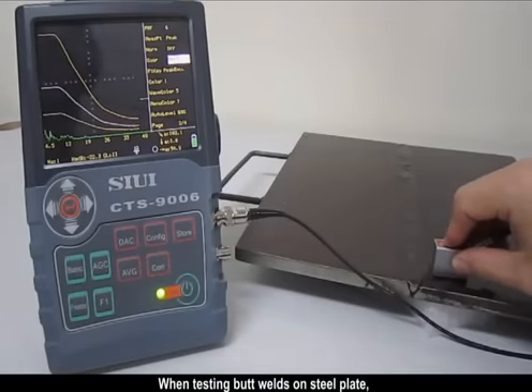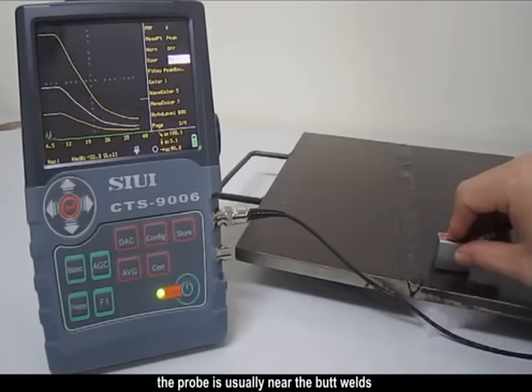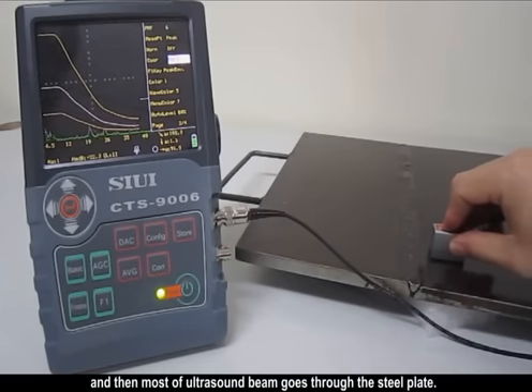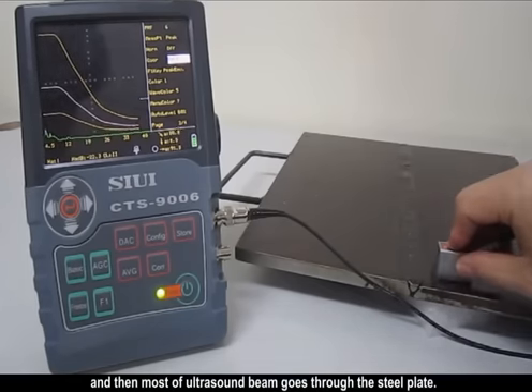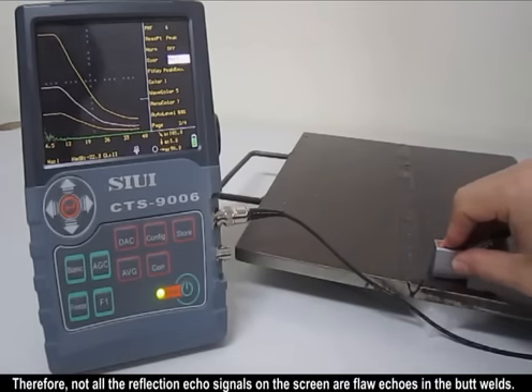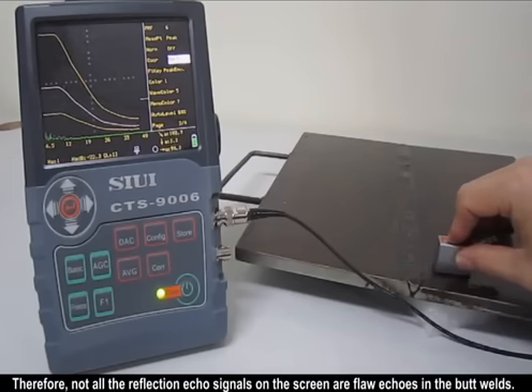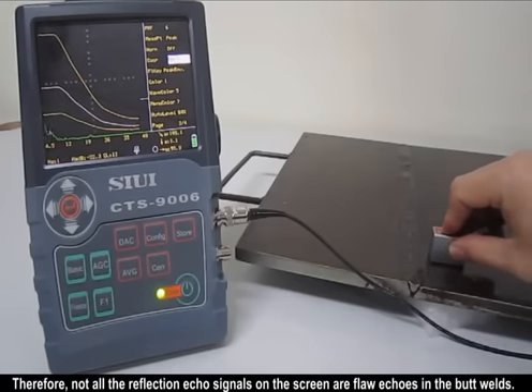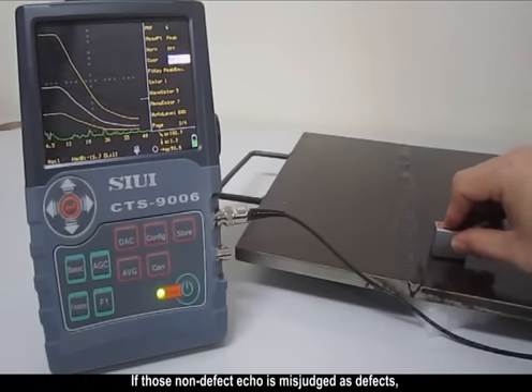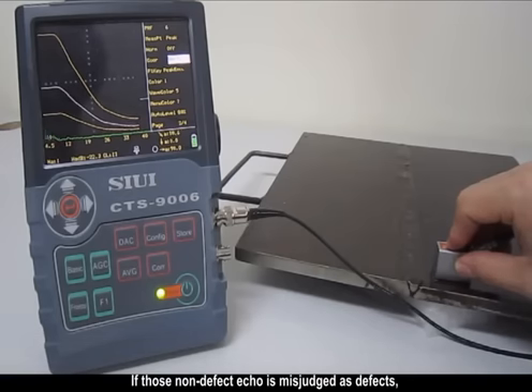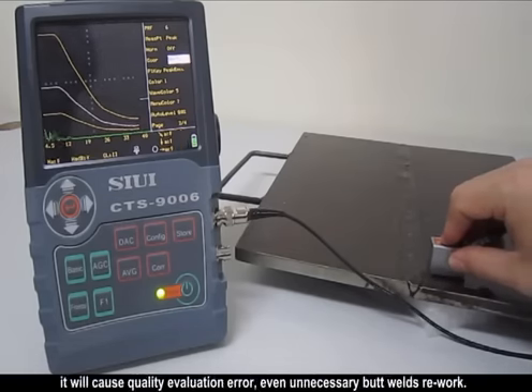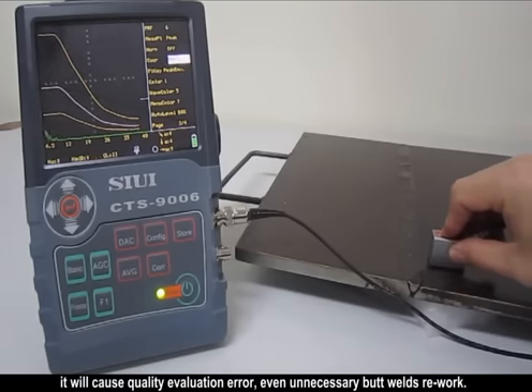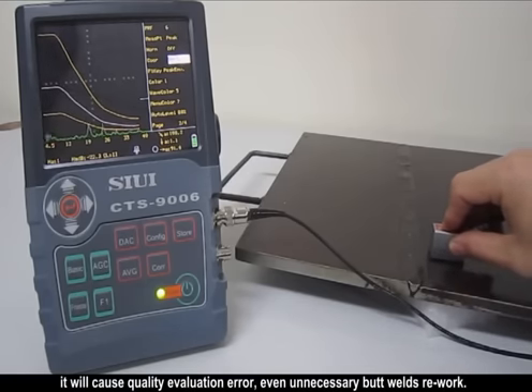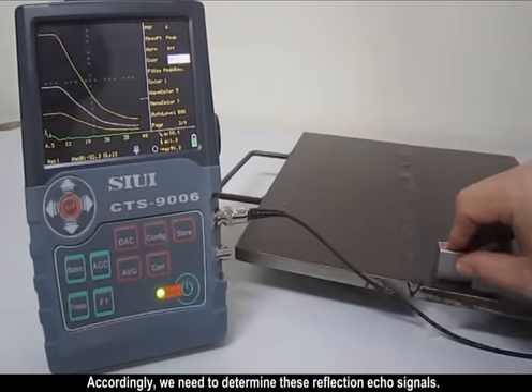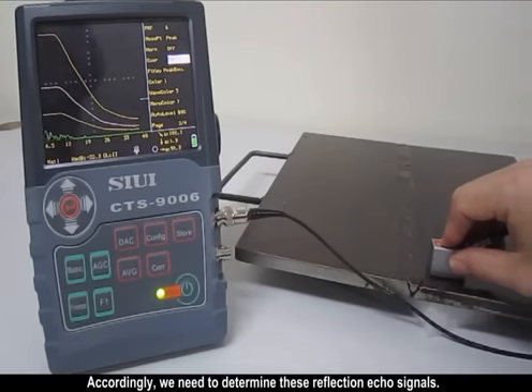When testing butt welds on steel plate, the probe is usually near the butt welds and then most of the ultrasound beam goes through the steel plate. Therefore, not all the reflection echo signals on the screen are flaw echoes in the butt welds. If those non-defect echoes are misjudged as defects, it will cause quality evaluation error, even unnecessary butt weld rework. Accordingly, we need to determine these reflection echo signals.